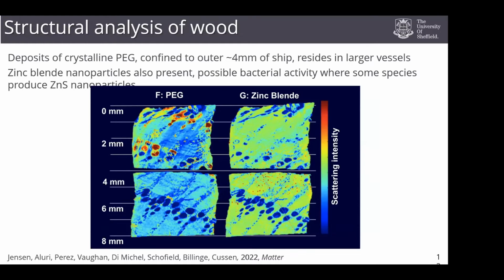Well, it turns out we're able to locate whereabouts in the wood this polyethylene glycol resides. And that's really fantastic because polyethylene glycol is carbon and hydrogen, very similar to cellulose, but we can tell the two apart using this technique. And this is the first time we've been able to locate how far into the wood, over those 30 years of spraying, that polyethylene glycol has managed to penetrate.